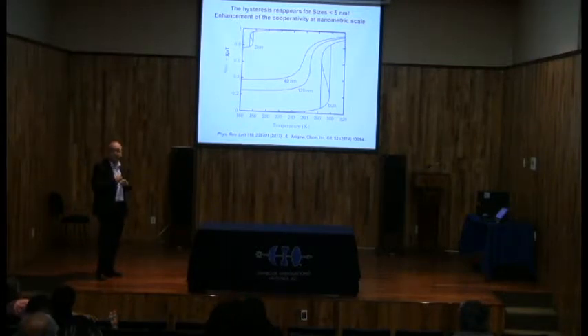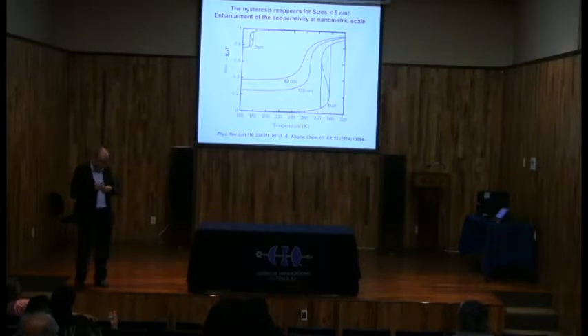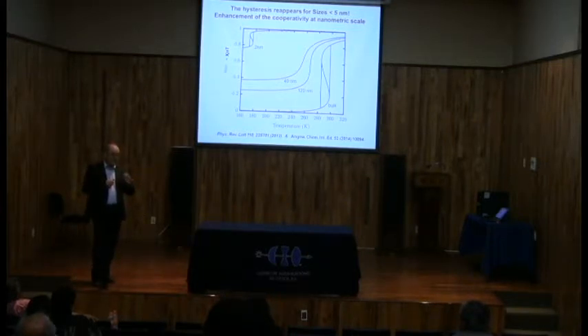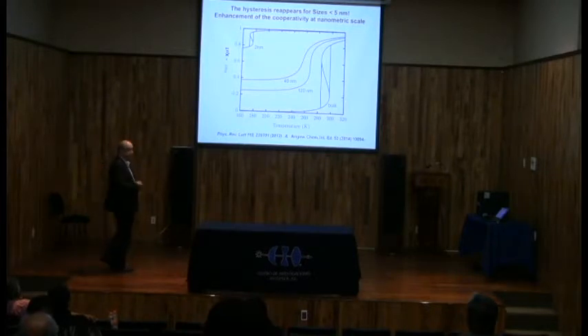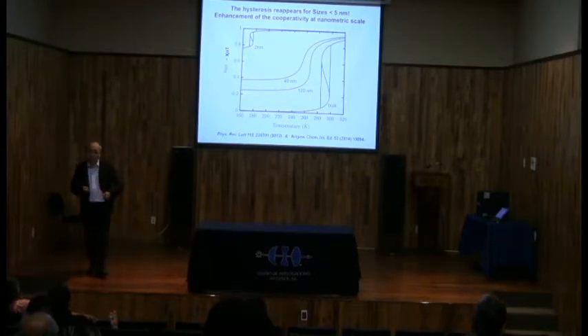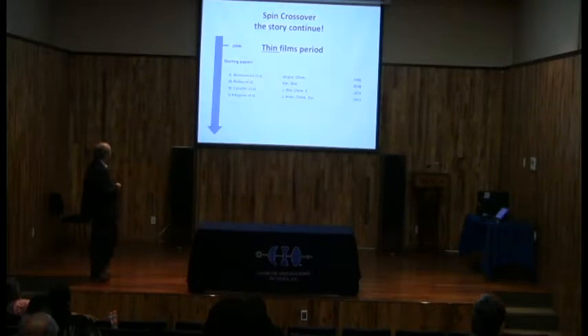This was very, very exciting results. That means that by stability, the hysteresis loop can be seen even at 2 or 1 nanometer nanoparticles. Okay? This is quite important for the density of the storage if you use the systems in devices.